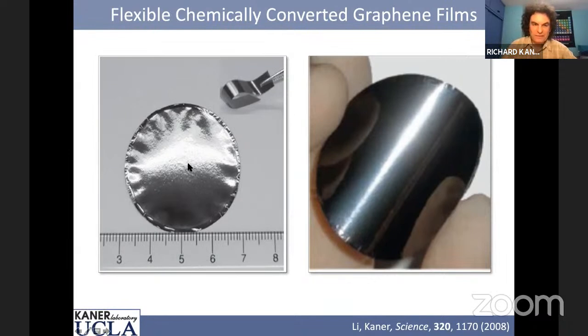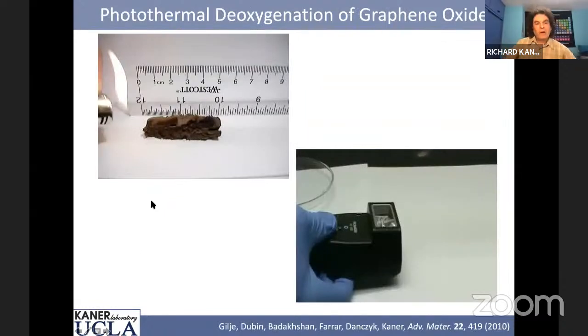Now you may ask, well, isn't that just graphite? Well, graphite's actually three-dimensionally ordered. It's AB stacked, but this material is just randomly stacked, but it's quite strong, and you can see it's highly reflective. Now, one of the things you can do with graphene oxide is you can freeze dry it, and then you get this material that looks like this golden brown material. And one of the early experiments we did is we just lit it on fire, and I'll show you that here.